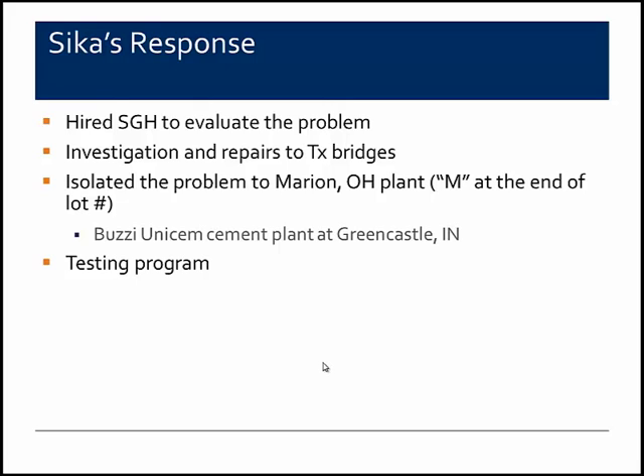They did check all of their other components of the grout and concluded that they did not contain any chlorides. In the process of doing this initial investigation, they also realized that they had shipped grout from this Marion, Ohio plant to many, many other projects. And so in addition to the repairs for the Texas bridges, they started a very large-scale testing program to help evaluate the issue nationwide.